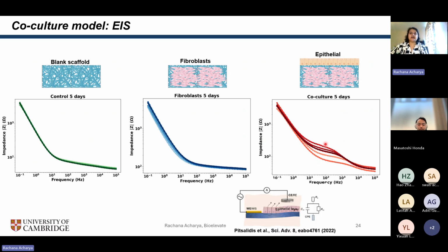And the way this functions is that we can model our epithelial barrier, or basically every component in this device, as an equivalent circuit element. So for example, the scaffold is capacitive and resistive. There is a resistance of the solution electrolyte. And then my cell monolayer, I'm modeling as a parallel resistor capacitor circuit, because the individual cells are going to act as capacitors, but the junctions, or the places where the cells are joining to form this monolayer, are going to have a resistive component. And then if I fit this measurement to this equivalent circuit, I can extract parameters for this resistance and use it as a metric of how strong my barrier is, or for barrier integrity. And this has been done in multiple publications.